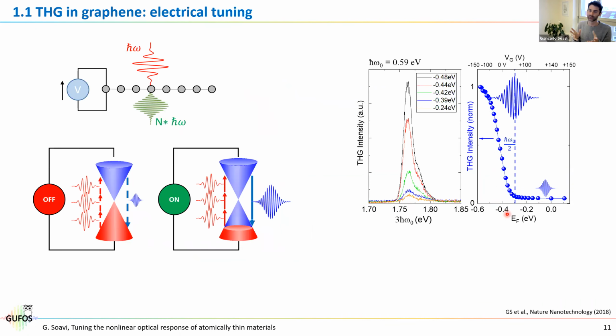So this is the first main result. And if you remember, the goal of this activity is to achieve, let's say, active control of frequency generation. So you can immediately see that this is indeed a gate tunable frequency converter, where by simply applying a gate voltage or by simply tuning the Fermi energy, we can switch on and off the third harmonic generation efficiency by more than a factor of 20. And this is due to the fact that we can move in and out from these multi-photon transitions.